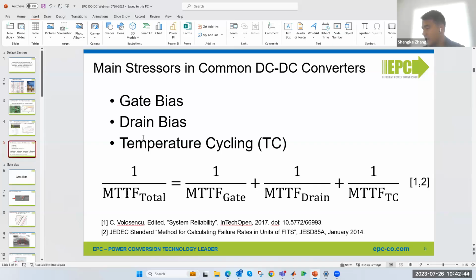If we take the mean time to fail terms together, what we have learned is that the gate is not really a problem. From the denominator point of view, so far we are looking at drain. From the intrinsic wear mechanism point of view, first, there's no catastrophic failure, even up to 120 volt over voltage switching. And I don't see anything there, the mean time to fail is very little. So that leaves us the last term, which is temperature cycling. For our chip-scale package part, temperature cycling, depending on mission profile, could be a limiting factor. But by adding underfill material, that should solve the problem.